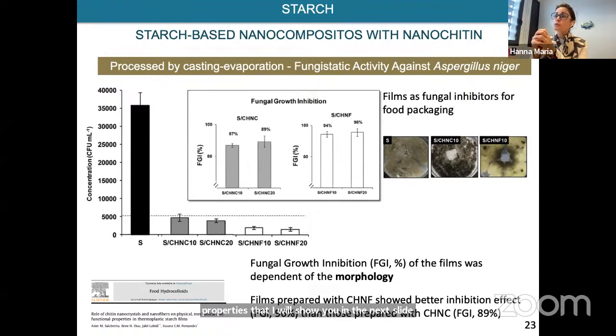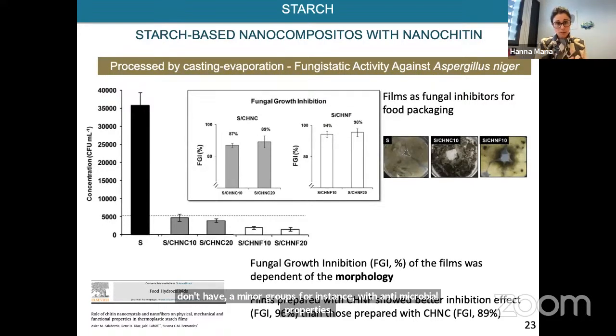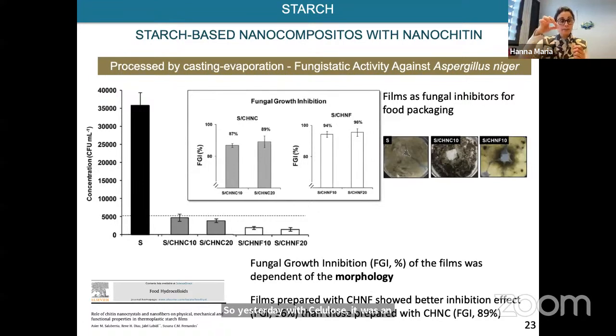But it was also to give some antimicrobial properties to starch, because starch, like cellulose, being glucose, doesn't have amino groups, for instance, with antimicrobial properties. So yesterday with cellulose, it was the incorporation of a silane derivative with NH2 groups. And here, what we did was to incorporate chitin, that has NH2 groups, to improve the antimicrobial properties of starch.